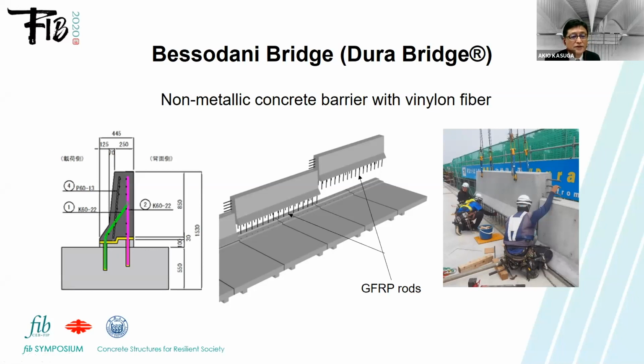But in this case, this concrete barrier is completely 100% non-metallic. Instead of steel fiber, we use vinylon fiber because the concrete deck is in a very, very severe condition. In Japan, we use de-icing salt during winter on the highway, so in order to avoid some small possibility of deterioration, we completely remove this risk by changing from steel fiber to vinylon.